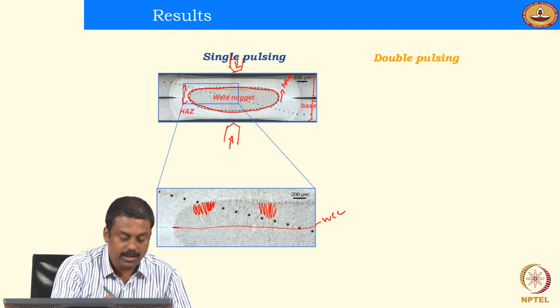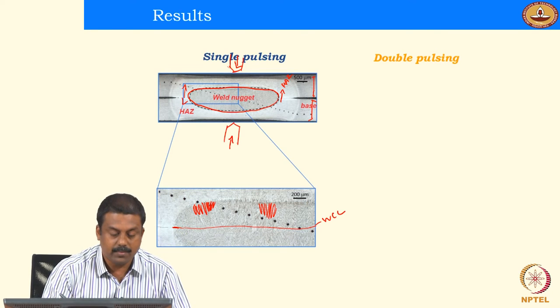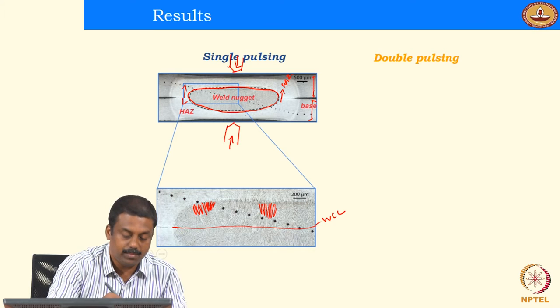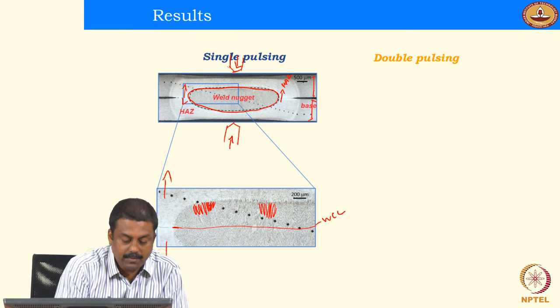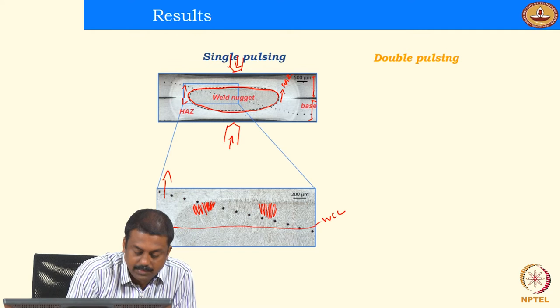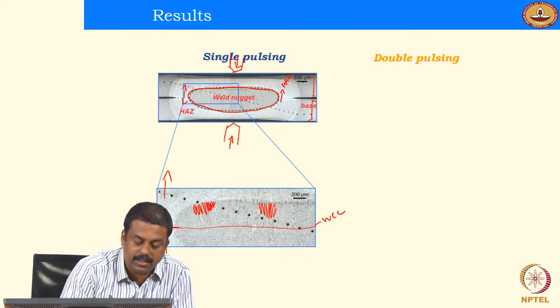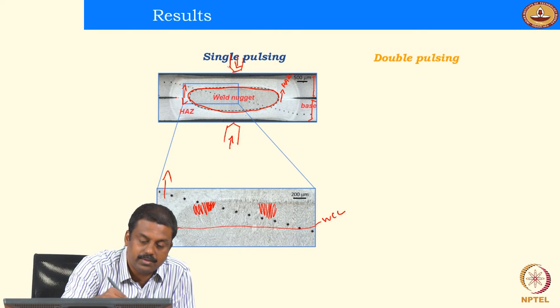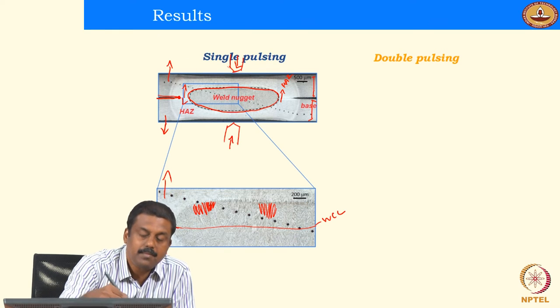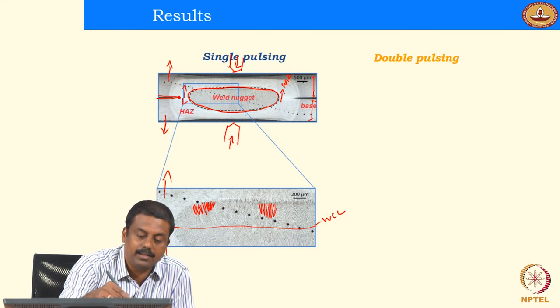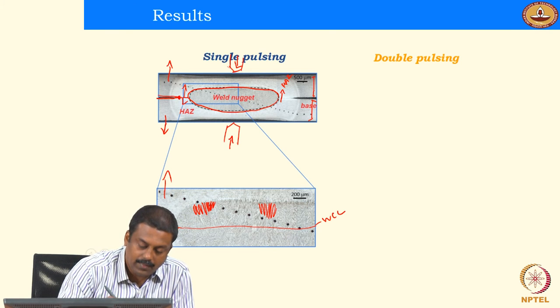Okay, so now if you apply load to this microstructure, when you are doing a cross tension test, for example, when you pull apart these two regions, what will happen? This is the region where you expect a failure, a crack to nucleate, because that is the interface which is there, and you also see this interface is like a notch, isn't it? So this interface will act as a notch, and then there will be a stress concentration at this point when you are pulling in a tensile direction as shown in this figure, and you will have a crack propagating along this weld center line.